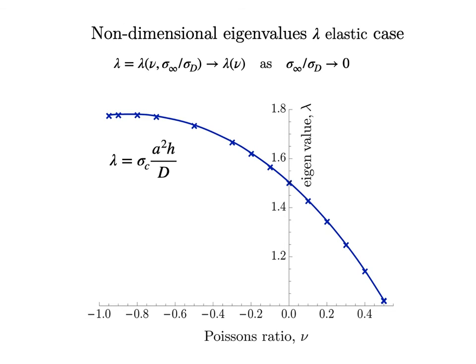Here it is assumed to be small, and the influence of Poisson's ratio is plotted in this graph. It's usually considered to be rather small and very often not included in analysis. And here it looks very drastic, because it goes from 1 at one end to 1.8 at the other end. But on the other hand, this covers an enormous, almost ridiculously enormous band,